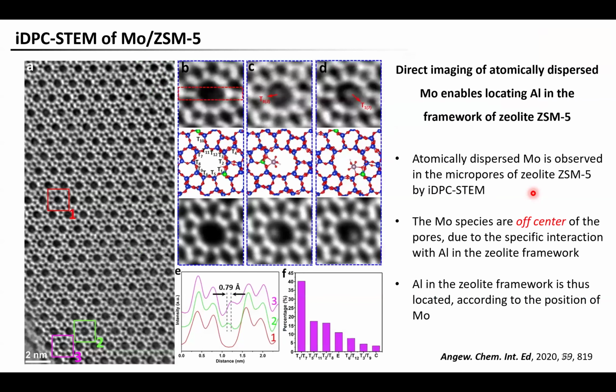The high electron dose efficiency makes iDPC-STEM a good choice for low-dose imaging, while the ability to image light elements and heavy elements simultaneously makes it suitable for studying host-guest interaction in nanoporous materials. And this is probably why iDPC-STEM has been extensively used to study zeolites. Zeolites are inorganic porous materials.